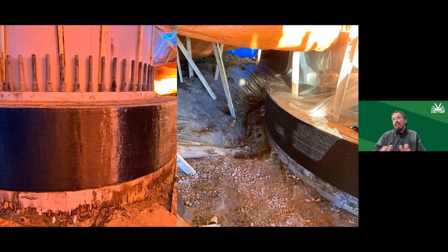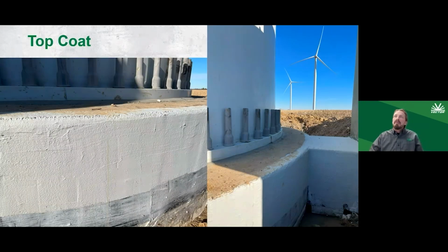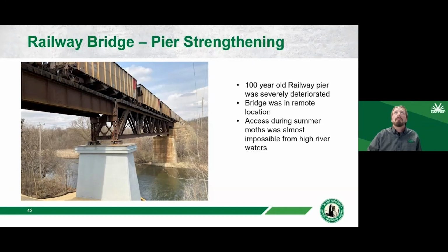I think this one received 6 layers, or 2 or 3 double layers of fabric. They get everything laid up, get everything cured, and then because this is going to be exposed to the soil and UV, at least on the top of the pedestal, they put a UV stable acrylic top coat over the top of the FRP fabric.